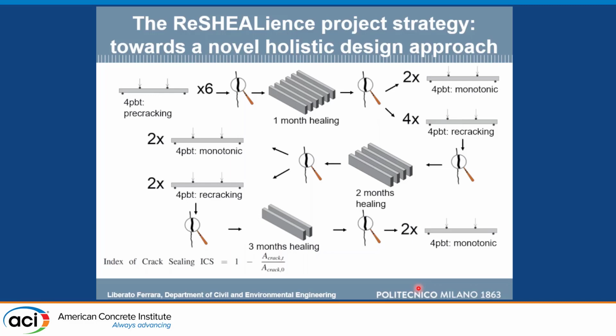We kept healing for 1 month in geothermal water, chloride water, different curing environments. After 1 month, we tested to failure some of the specimens to see the evolution of the performance, but some other ones were simply re-cracked and put back to heal. And after 2 further months, re-cracked and put back to heal, and this went up to 6 months or 1 year in some cases.